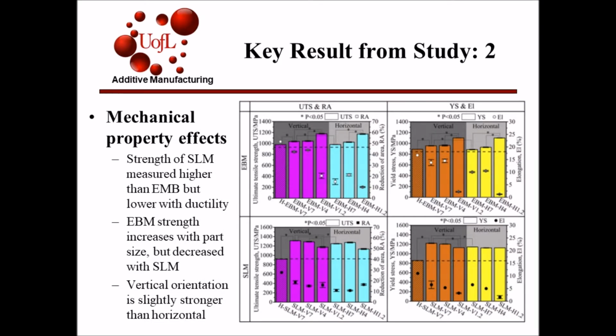The graph on the right shows the ultimate tensile strength, yield strength, and elongation measured for the various samples printed on SLM and EBM. As shown in the graph, the strength of the SLM samples measured higher than those of EBM samples, whereas the ductility is much lower. For EBM, the strength increases with part size. However, for SLM samples, strength decreased with part size. For both EBM and SLM, the strength and ductility along vertical orientation is slightly higher than along the horizontal orientation.